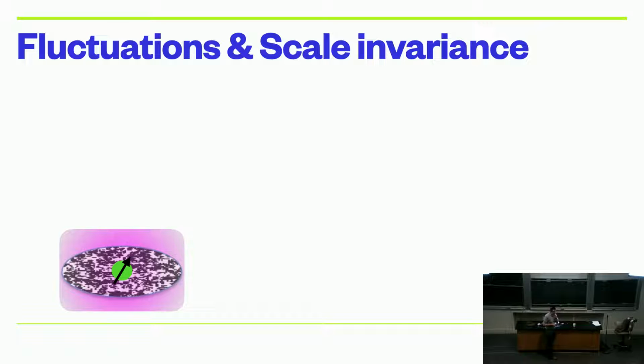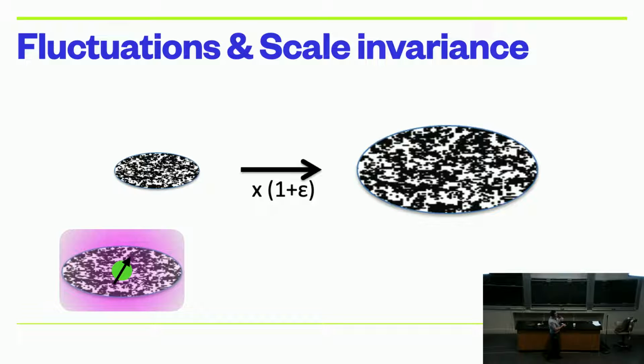Now, something really interesting happens in this fluctuating state, and that is what's sometimes called a statistical symmetry. It's an emergent behavior of the system where you get what's known as scale invariance. What that means is that if I looked at the spatial profile of these fluctuations, so imagine this is real space in a ferromagnet, then as I go closer to the transition, I will get the same kind of profile of fluctuations, but now over longer length scales. It'll just be a multiplicative factor connecting the fluctuations in one part of the system to the fluctuations in the other. This is what sometimes people call fractal behavior or scale invariance. It just means that as the system approaches its phase transition, you have these spatial fluctuations of the spin that don't have an intrinsic length scale to them, except for a cutoff scale.